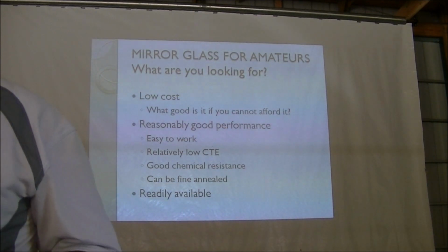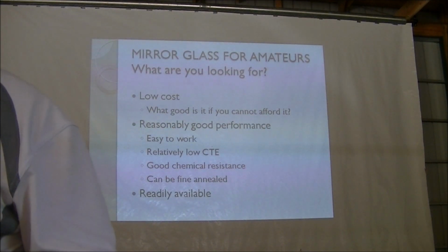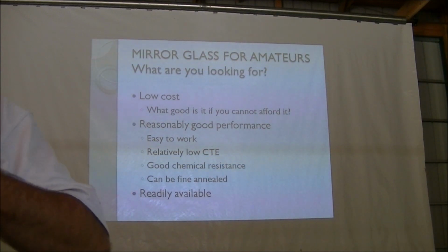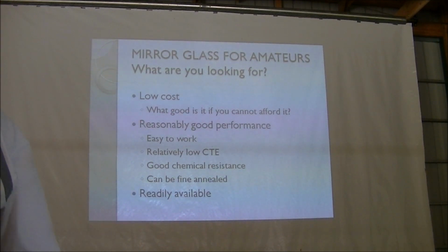But historically, people have pointed out to church windows that appear to have sagged over time, and they also look at an elasticity that glass has, where it will bend and hold its shape for a period of time in its bent position, but eventually it will relax back to its natural form. So years and years ago, when they were trying to determine what was the largest size of a lens that was practical for an achromat, they thought, well, like the Yerkes 40-inch or maybe the 42-inch that the French made might be the practical limit. The reality is that sagging of glass due to flow is not an issue. You have mechanical sagging, that's something completely different.